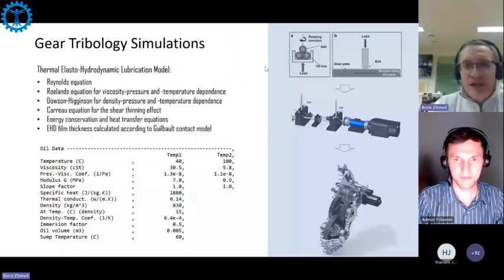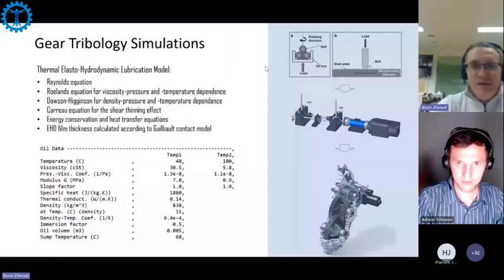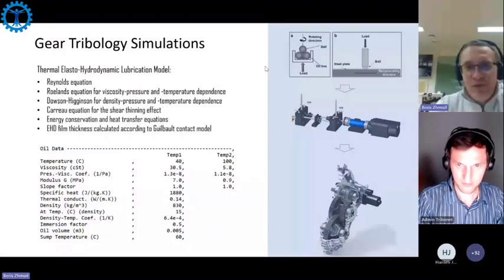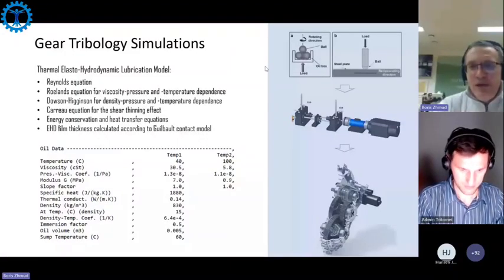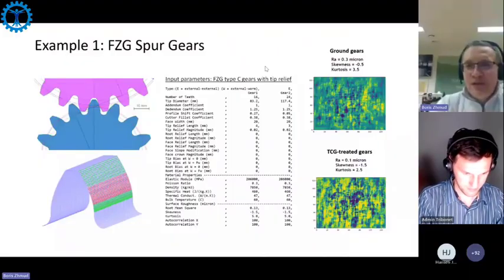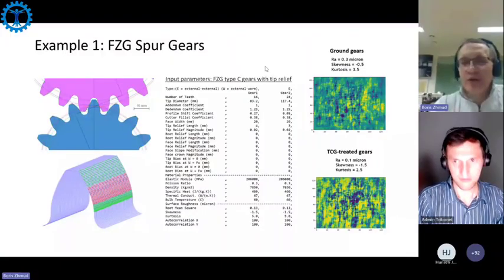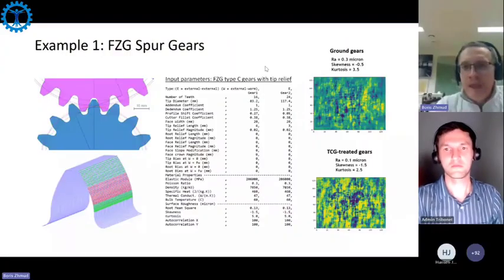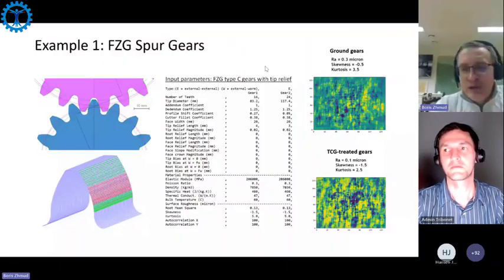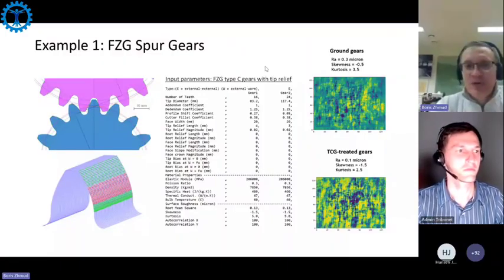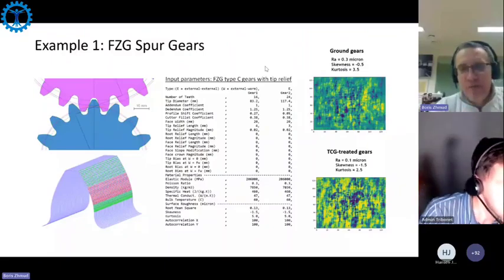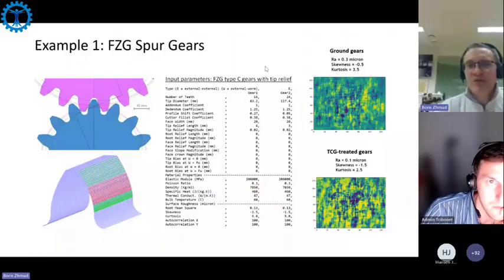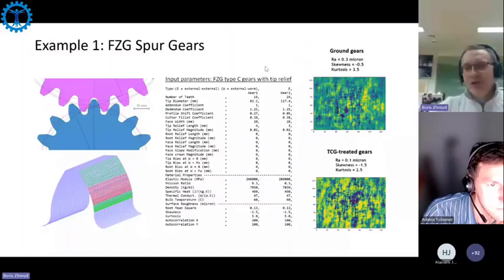Yeah, so this is just an example, I would say some input which you provide, very simple spur gears for FZG testing. We produce one gear which is representative of surface roughness of conventional ground gears, roughness 0.3 micron, Rz would be around, I would say 3 micron in this case, very little skewness. So then we go to tribo-conditioned gears. Tribo-conditioned gear is a gear which is processed by our mechano-chemical process. It has much more negative skewness, which means the surface is more like a plateau-like surface.